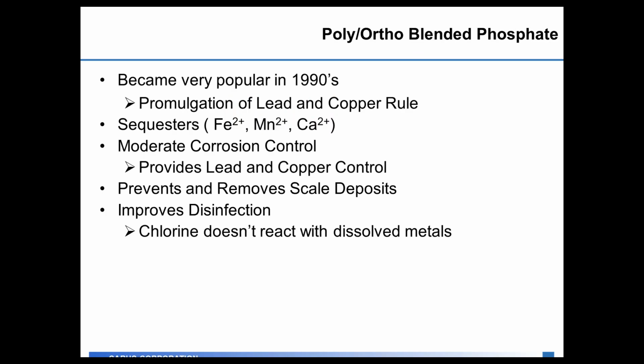So the combination of poly and ortho blended phosphates became very popular in the 1990s when the lead and copper rule came about. A lot of plants, especially groundwater plants, had to do both sequestration and corrosion control at the same time. So they chose products that combined both poly and orthophosphate to give them both of those benefits at the same time. They would provide the corrosion control they needed to meet the lead and copper rule, as well as sequestering the iron, manganese, and calcium carbonate in the distribution system.